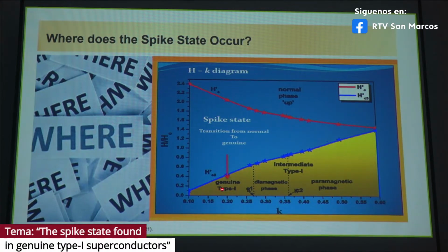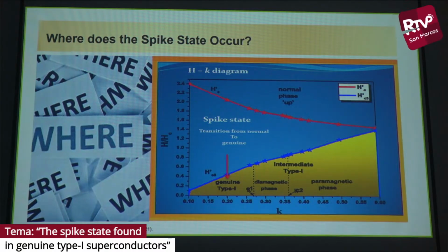We can divide this into regions. One is the intermediate type 1 superconductor. The intermediate type 1 superconductor allows that, when you decrease the field, vortices appear inside of this kind of type 1. Type 1, as most people say, has no vortices inside. Yeah, sorry, for bulk materials. But here in the mesoscopic scale, we have vortices inside of them.